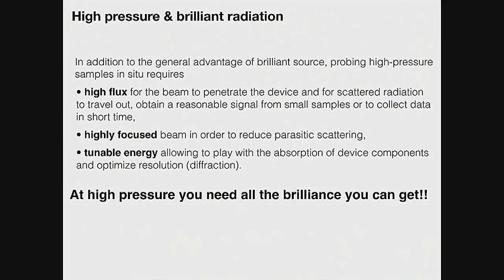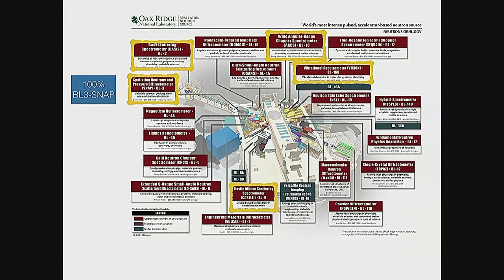You want a beam of the right size, so it goes through the window and gets to the sample, and it doesn't illuminate everything, all the device, because of course everything will scatter your radiation. So you want to minimize the parasitic scattering and optimize your sample to parasitic scattering ratio. You want a tunable energy if your technique allows you to select the energy. So you can select your devices, your materials to go through, and again minimize absorption and scattering of this material and optimize your signal. So of course, high pressure is very thirsty for brilliance.